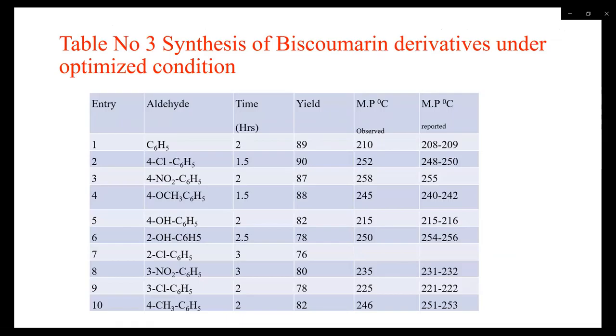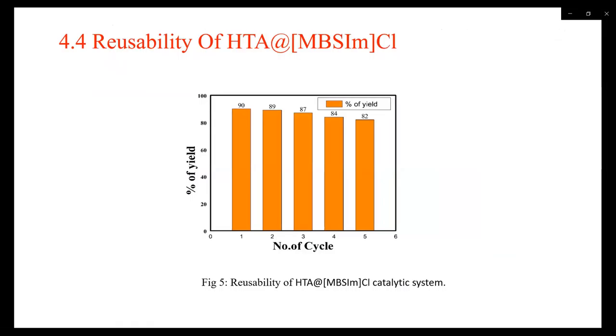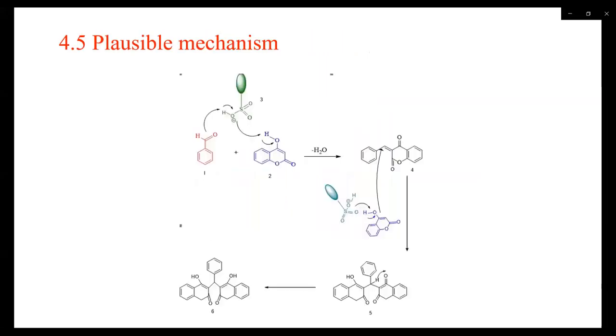We extended our reaction and synthesized different derivatives of this coumarin. As immobilized ionic liquids are well known for their reusability, we recovered the catalytic system after completion of the reaction and further used it up to the fifth cycle, without significant loss in catalytic efficiency. So the plausible mechanism of the given reaction for the synthesis of bis-coumarin proceeds through Knoevenagel condensation, followed by Michael addition, and the intermediate undergoes intermolecular rearrangement to synthesize the bis-coumarin.